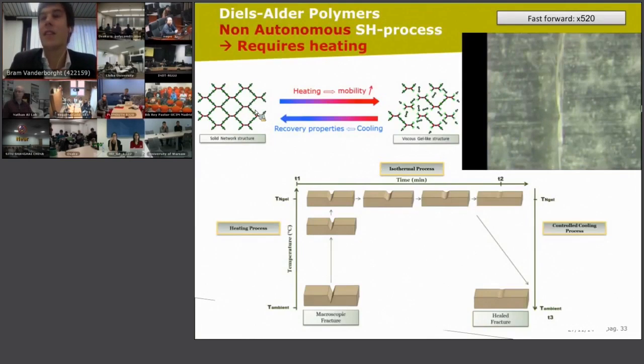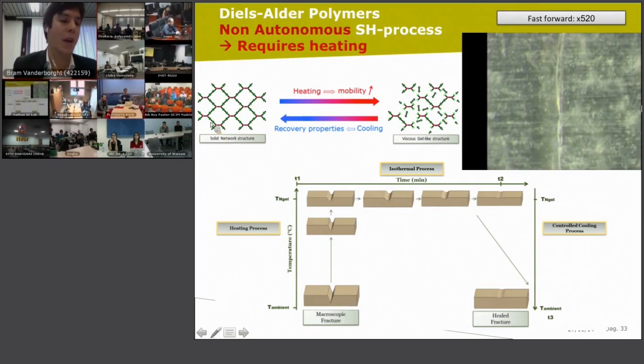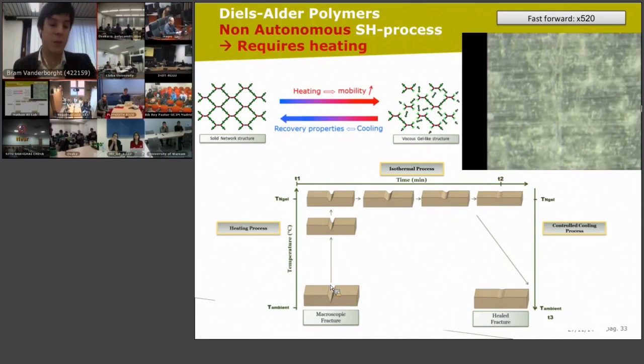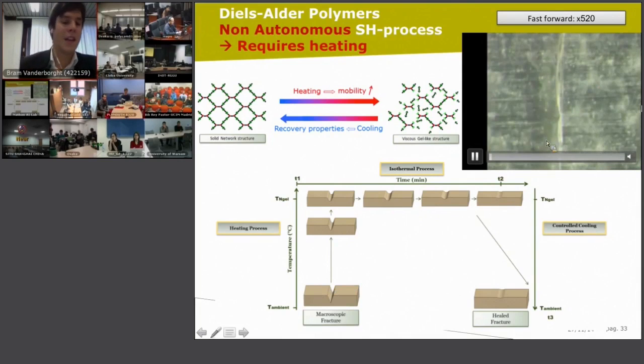On the next slide, you see on the right a video of the self-healing capabilities. You see that there is a cut, and gradually this cut is self-healed. What's in fact happening is that you have a solid network structure at room temperature. When you heat it up, you increase the mobility of those polymer strings, so you obtain a viscous, gel-like structure, and then the cut gradually heals. Then comes controlled cooling; this whole cycle of heating and cooling has to be done on a very precise profile. Then you see that the cut has disappeared.